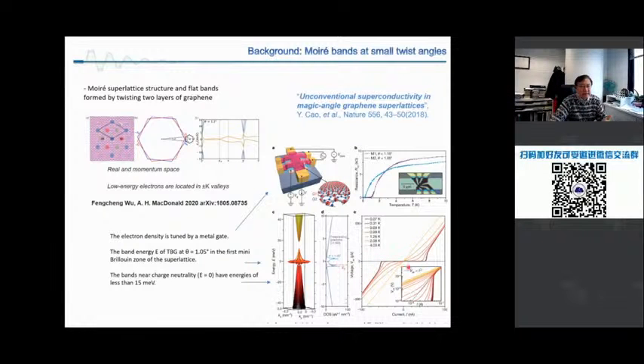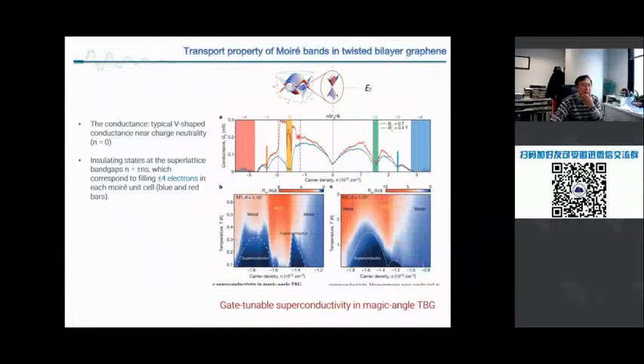And this is also the evidence that you have energy gaps, superconductivity. That means the superconductivity persists, still there until a certain high field. This is all the superconductivity signature. If you look at the conductance, this is the Dirac point. So normally you have a V-shaped valley in the conductance. But once you twist, at a certain filling, this is a full filling. Full filling, I see conductance is almost 0. It's very insulating. But at half filling, for example here, you see a very high conductivity. Right? It basically is a superconductivity state.